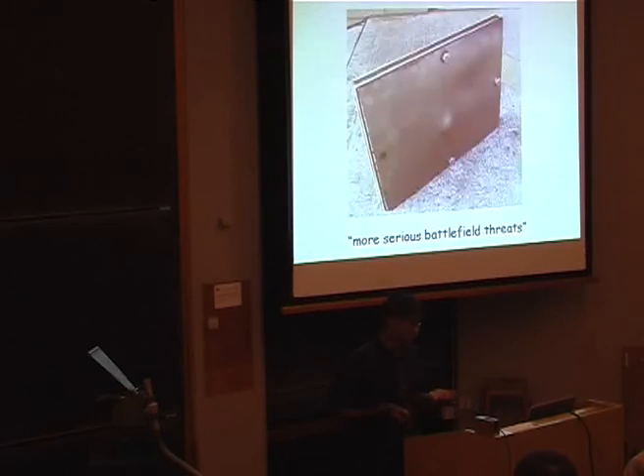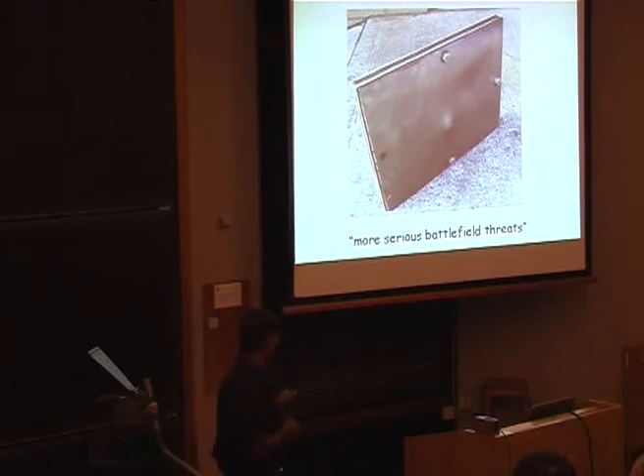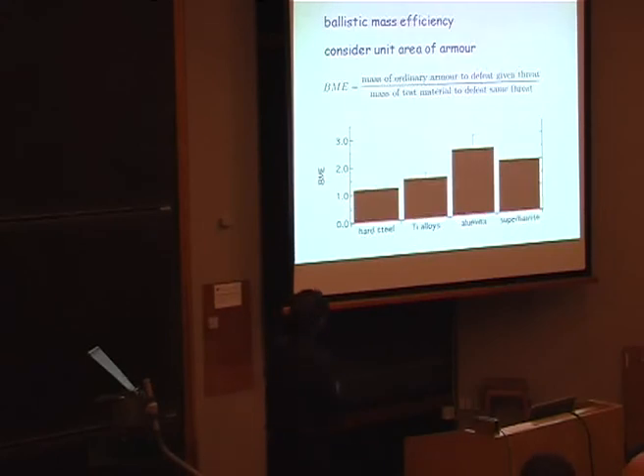If you test the strength of this at very high strain rates, then it yields at about 10 gigapascals. So that immediately suggests an application, armor. And it turns out that this is extremely good at stopping what they call more serious battlefield threats. I'm not told what those are. And indeed, it outperforms titanium or the normal armor, and it outperforms alumina in the sense that it can take multiple hits. Now, there are three other major applications which are in progress, which have nothing to do with armor, but civilian applications. But I can't talk about them right now.